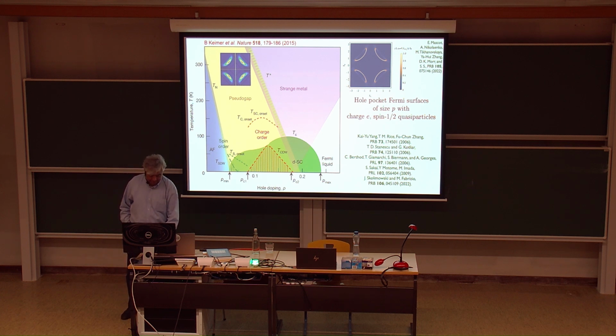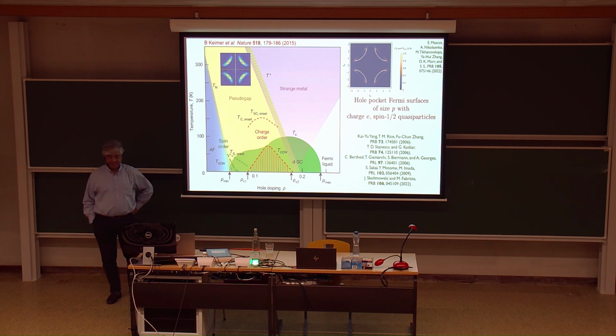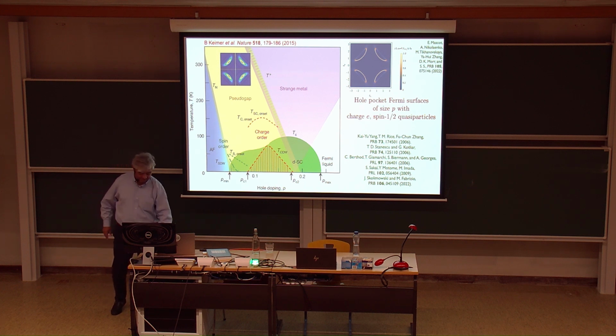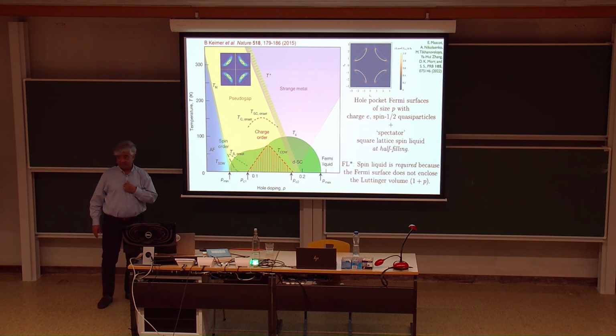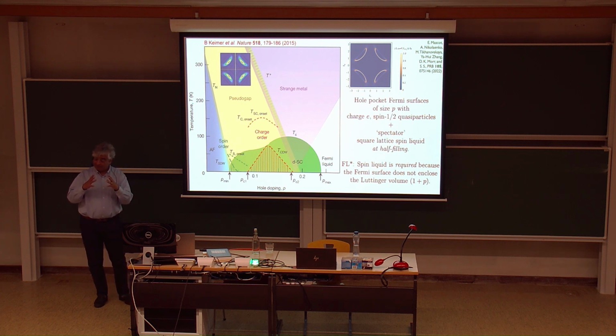Okay, so what I was starting to say earlier, once you have hole Fermi surfaces of size p, you have done something that's not allowed by everything we learn in condensed matter physics in the textbooks. You violated the fundamental Luttinger theorem, which is that the Fermi volume enclosed by the Fermi surface should be the density of electrons, modulo 2. So here the density of electrons is 1 minus p, or in terms of holes, 1 plus p, but you've got now hole pockets of size p. So you're missing 1 electron or 1 hole per unit cell inside the Fermi surface.